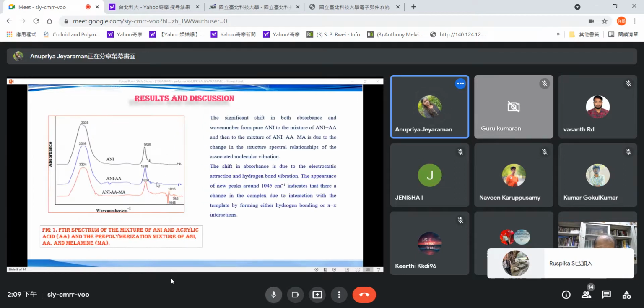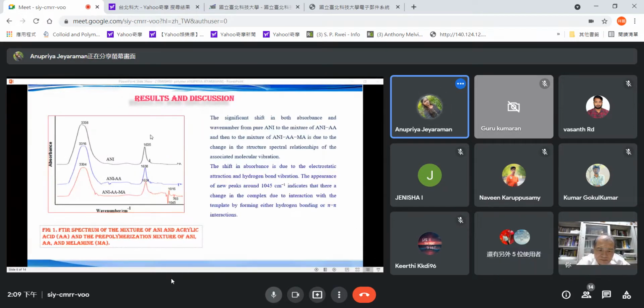The conducting polymer was confirmed by FTIR analysis. This black one is polyaniline. Here we see 3338, an NH stretching vibration, and 1635, a C=N stretching vibration. The second one is aniline with acrylic acid. Here 1300 centimeter minus 1 is a C-NH stretching vibration and this 1638 is a C double bond stretching vibration. The third one is the MIP. Here 3300 is an NH stretching vibration, and 1634 is a C double bond stretching vibration.